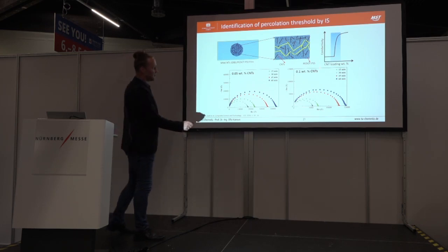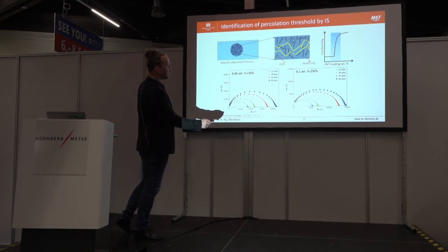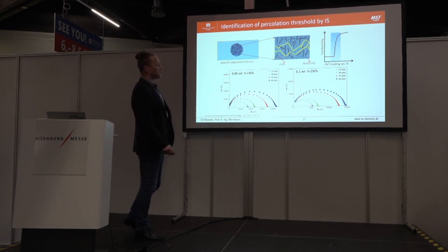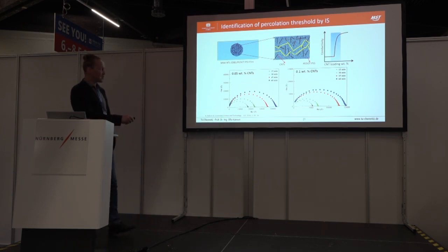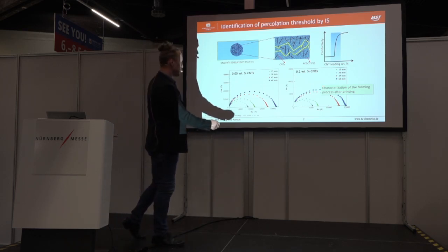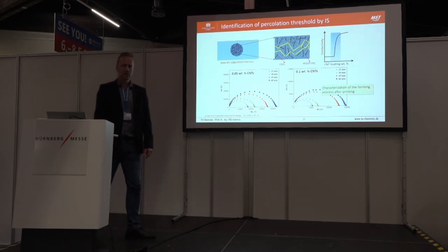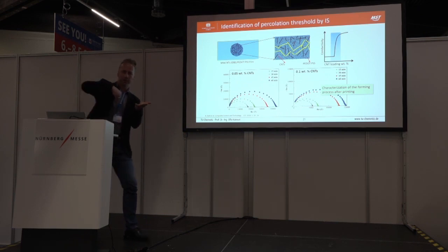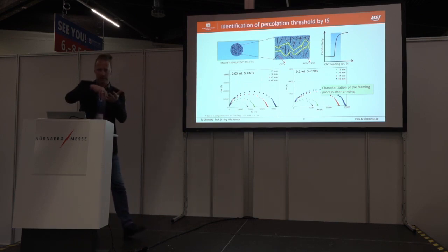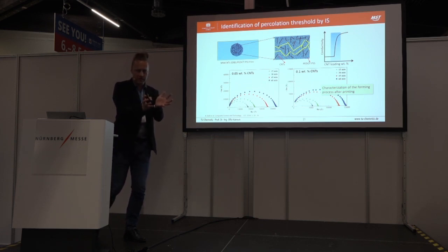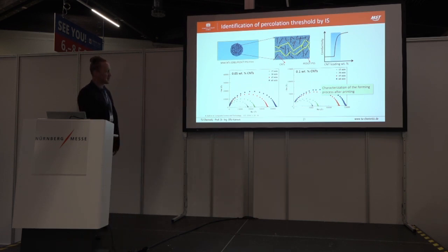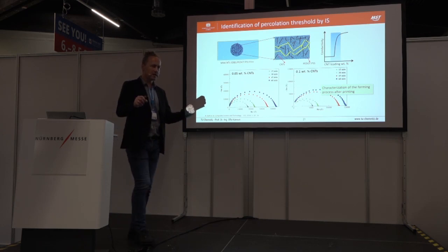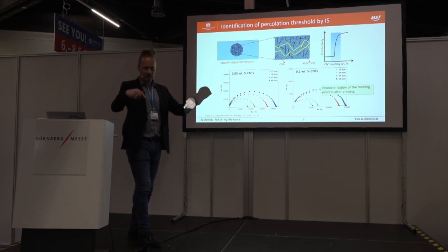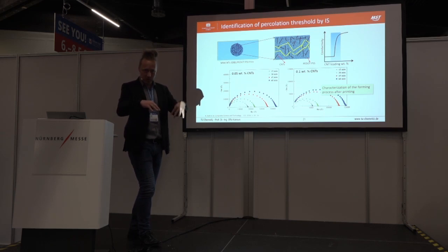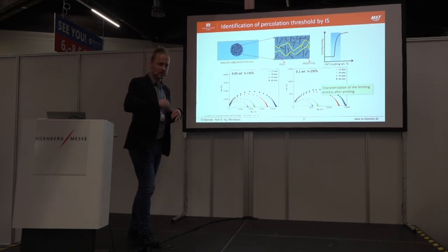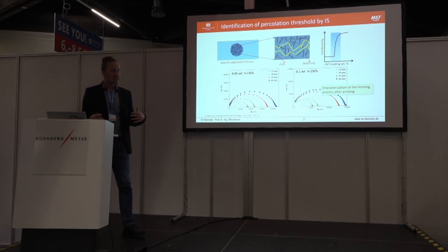So here you see first a diagram: the conductivity depends on the concentration of the CNTs. And what you can see here is a characterization of the forming procedure. We have the printing, and afterwards, in the drying procedure, the forming of the structure, followed by impedance spectroscopy. So we can measure, okay, analyze it in the lab beforehand for sure. What is the best time to continue with your process for the next step?